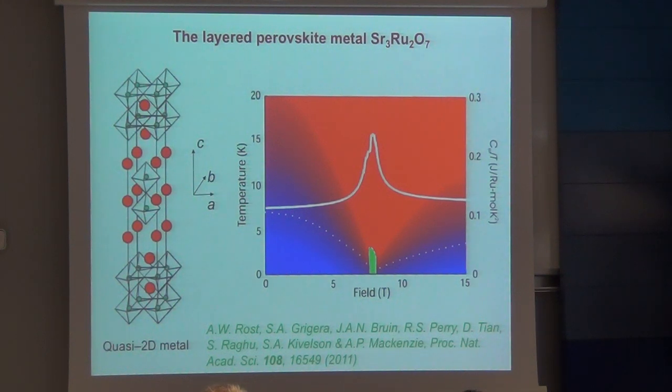There's no symmetry breaking going on, but you can still have a quantum critical point because in that circumstance you'd have a line of first order transitions ending in an endpoint, and this is going quantum critical because you're tuning the endpoint towards T equals 0. Okay? And we're also able to study various thermodynamic crossovers that show that the thermodynamic scales are being suppressed on exactly the same range of temperature and fields as the transport looks anomalous.